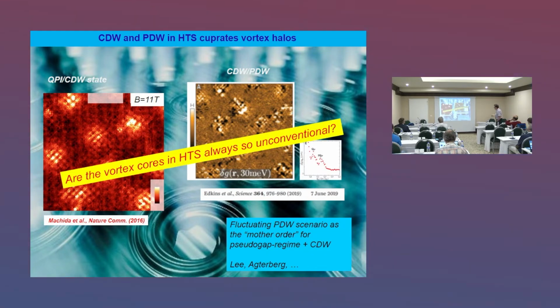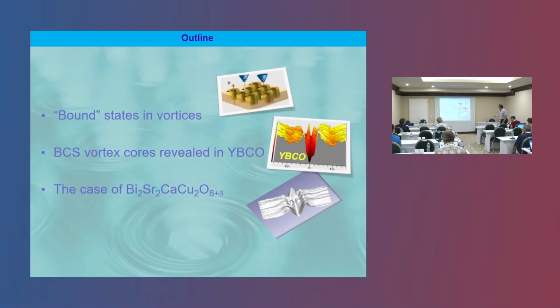But the main question, and this is something we have been looking for since many years, is to try to see from the vortex cores whether at some point they might still reveal some BCS behavior and be more conventional than maybe expected. So for the outline, I will show rapidly what we see by STM in vortices, like the bound states, which are predicted by BCS. And then measurements we've been doing a long time ago in YBCO, and more recently to dig out the vortices. And finally, the case of BISCO, which revealed unexpected results.